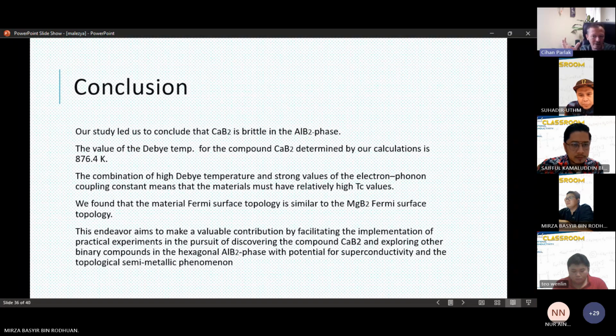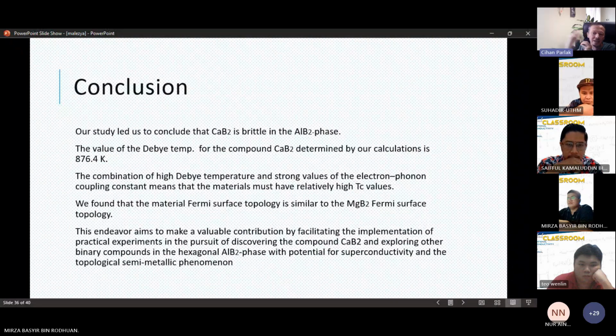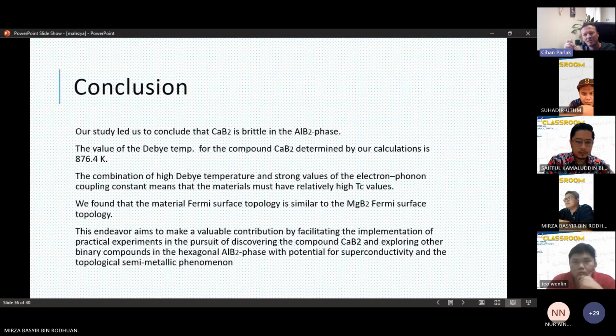The hypothetical calcium diboride, as I said, is not observed experimentally, but if you calculate the cohesive energy, it says calcium diboride can be synthesizable, and our phonon frequencies show that if we synthesize calcium diboride, it will be dynamically stable, and our elastic constant calculations show calcium diboride is mechanically stable, but for now it's not synthesized. And the value of the Debye temperature is about